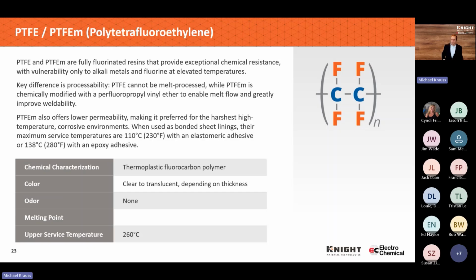PTFE's got an extremely high molecular weight. It doesn't actually melt, and it has to be processed via some other unique systems that were designed just to handle that. So that's critical. Modified PTFE is kind of a hybrid between the PTFE and the PFA. So the diagram on the right shows you what PTFE looks like. It's just this really long carbon chain backbone with every hydrogen substituted. So same concept as what we saw with polyethylene in the beginning, long carbon backbone, but here every hydrogen has been replaced with fluorine.